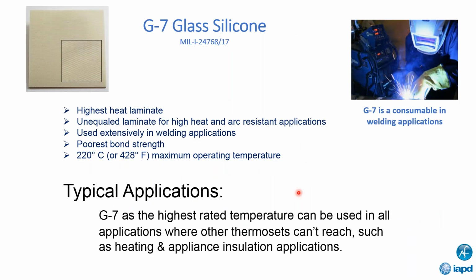G7 glass silicone. This is a glass material made with silicone. It's our highest heat laminate. It goes up to 220 degrees C or 428 F. This is typically used in high heat and arc resistant applications. And then on the right-hand side, the G7 is used extensively as a consumable in welding applications. So another application, if you have a welding equipment manufacturer nearby, I would look to them as possible for tube applications as well as G7 in general.